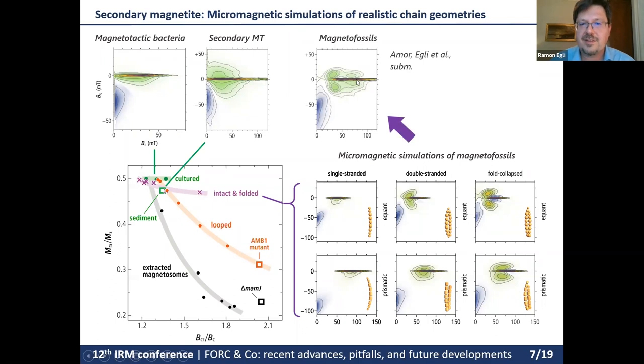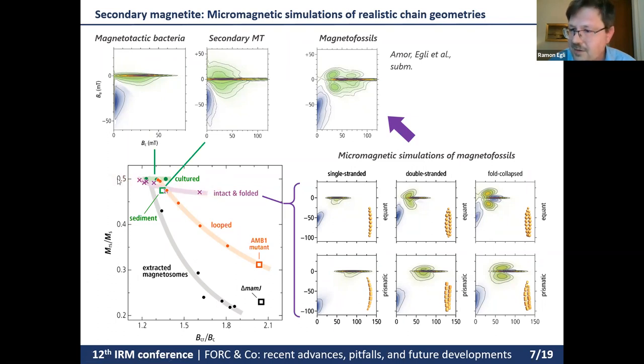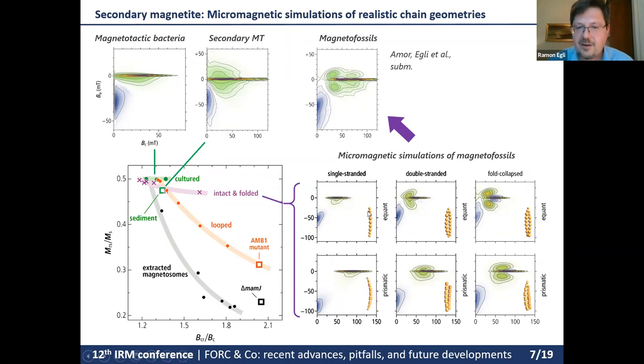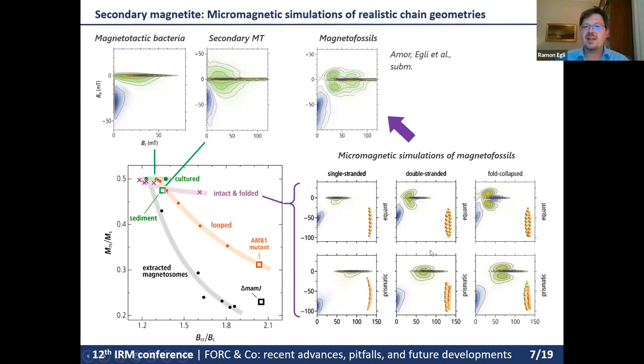Putting together all these signatures, we get something vaguely similar to the natural signature. Most importantly, the trend maintains a high remanence ratio, like in classical single domain particles. The reason is that these structures maintain a strong uniaxial anisotropy, which enables the single domain state of the chains to be preserved even in zero field — giving the high remanence.